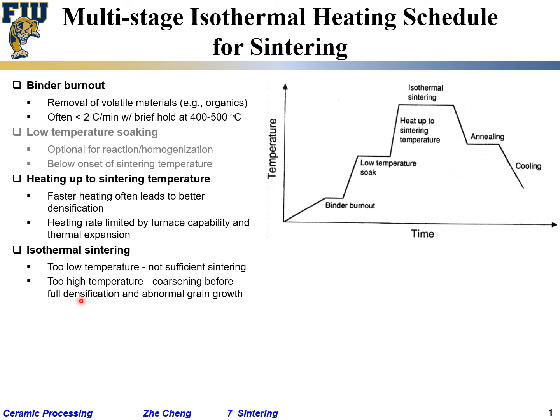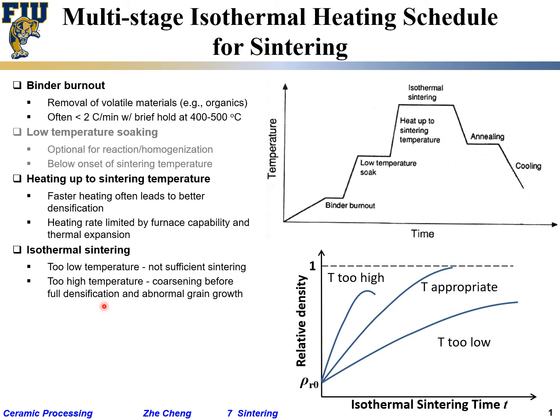But coarsening can happen without densification, which means the particles are getting larger and larger, but in between the porosity has not been removed. So those are bad, because in the end, you have huge grains, but then a lot of porosity in them, which means that mechanical property would not be good. And if you are talking about other properties, may also not be good, like electrical or thermal. Okay? So it's always a compromise, not too high, not too low. Okay? And here we're showing the conceptual idea.